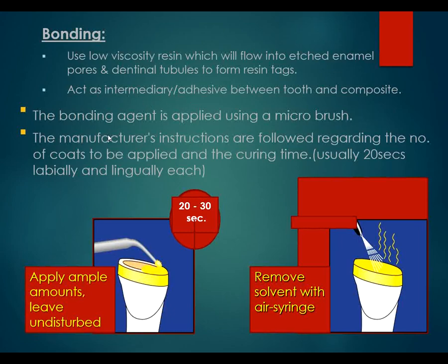The bonding agent is applied using a microbrush, as you can see in the picture, for 20 to 30 seconds. Multiple coats of bonding agent should be applied. The manufacturer's instructions are followed regarding the number of coats to be applied and the curing time, usually 20 seconds labially and lingually each.